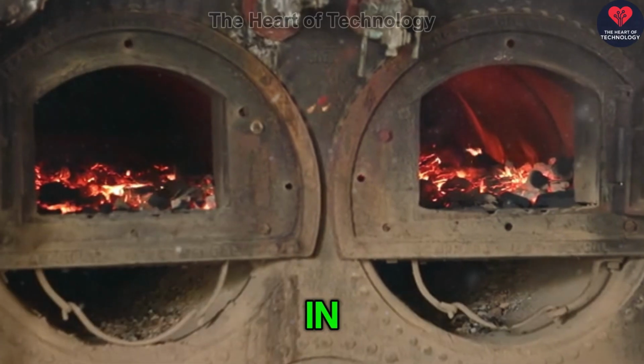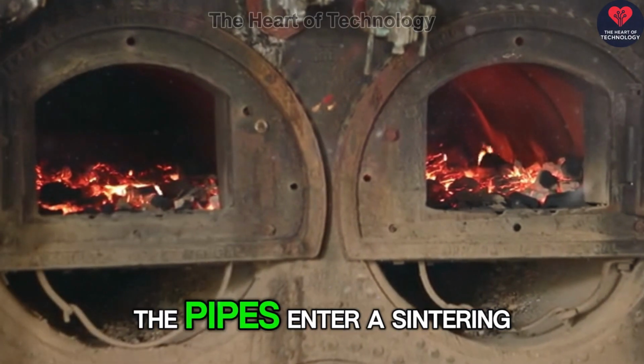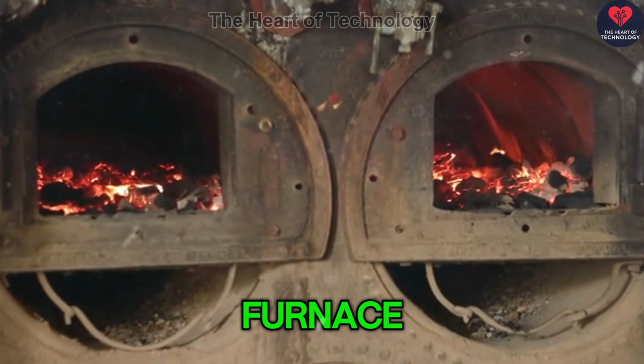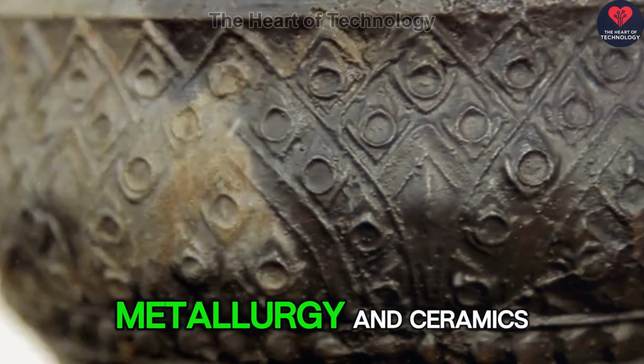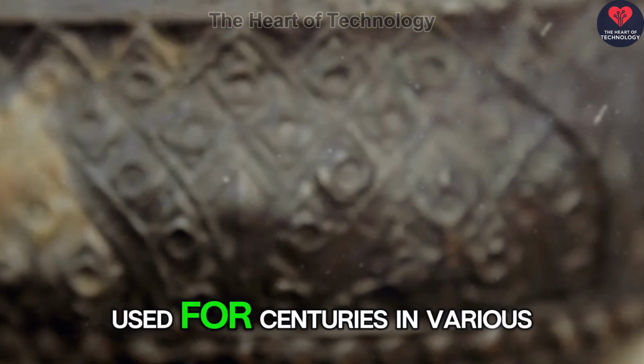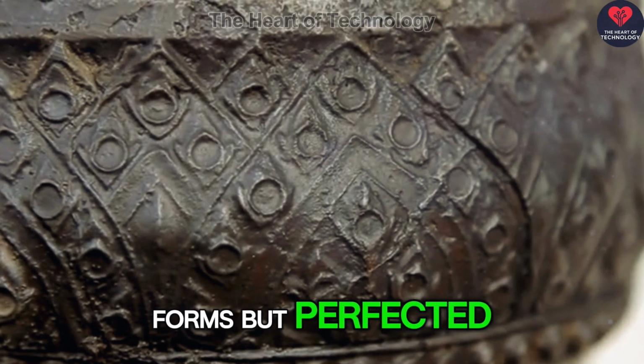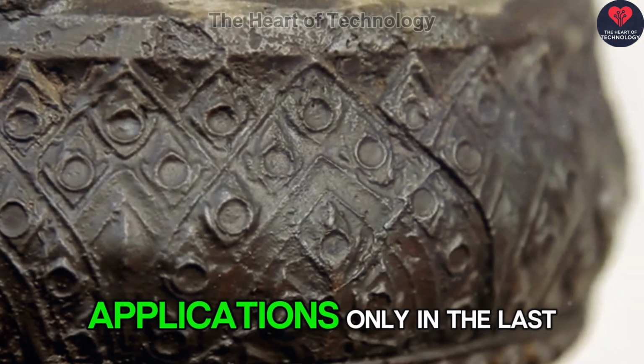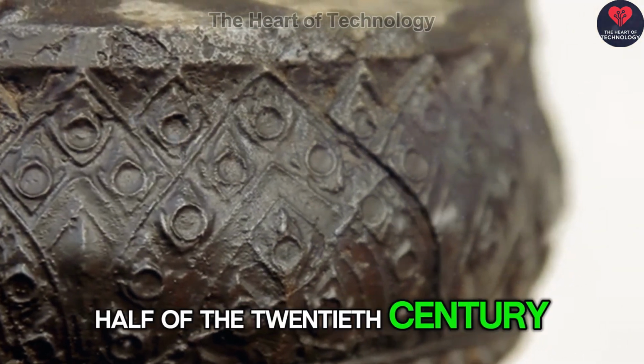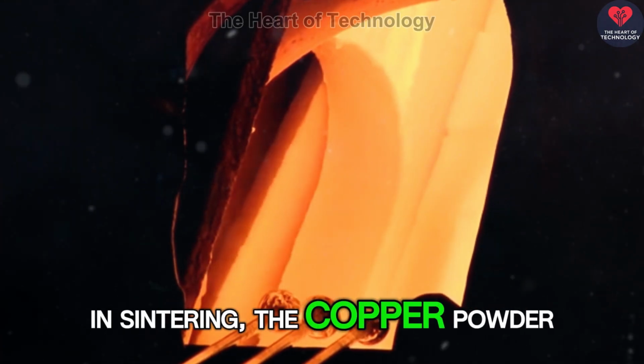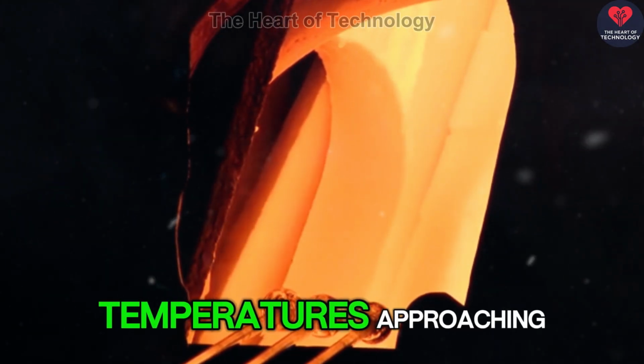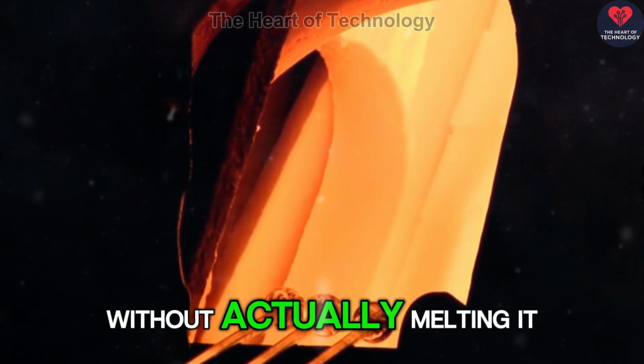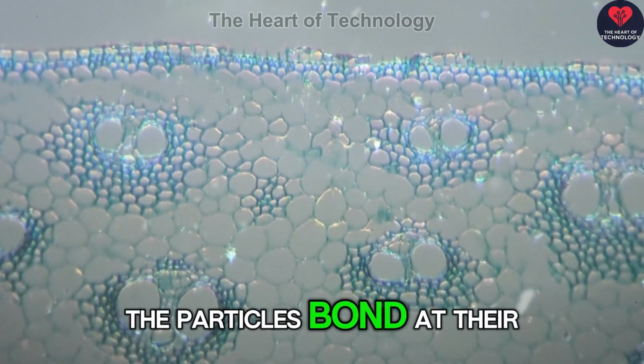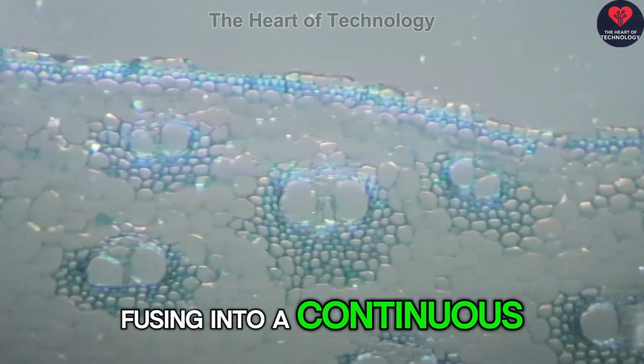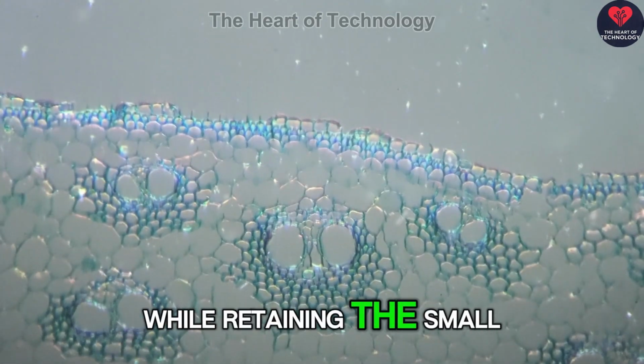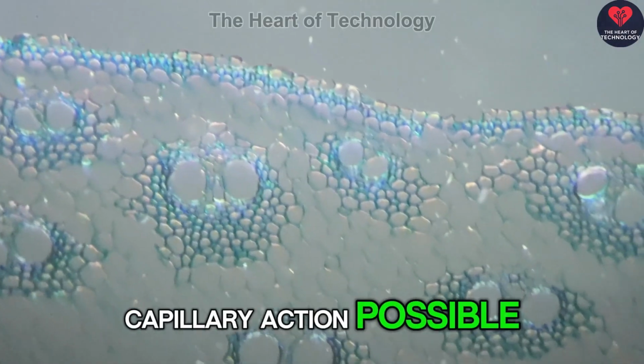Once the copper powder is in place and the tubes are sealed, the pipes enter a sintering furnace. Sintering is a process borrowed from metallurgy and ceramics, used for centuries in various forms but perfected for modern engineering applications only in the last half of the 20th century. In sintering, the copper powder inside the tube is heated to temperatures approaching the melting point of copper without actually melting it. The particles bond at their contact points, fusing into a continuous porous matrix while retaining the small air gaps that make capillary action possible.